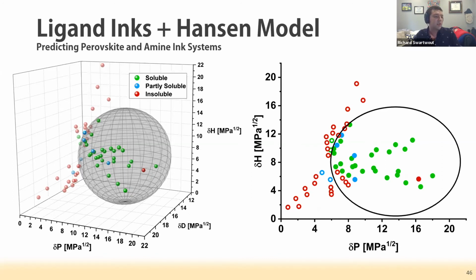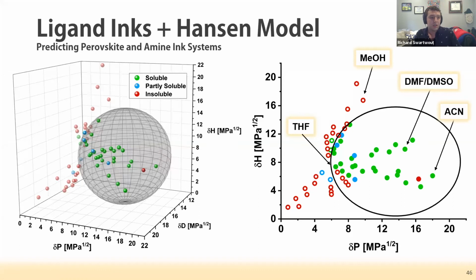As shown here is all the ink systems that went into this model with the interaction radius of the methylammonium lead iodide. This is specifically methylammonium lead iodide formulation. Just to give your bearings on where solvents sit within the space, THF is about here. More aggressive solvents like DMF and DMSO are in the higher polarity regime, acetonitrile as well, and then methanol, of course, is more hydrogen bonding, which is polar within this model.